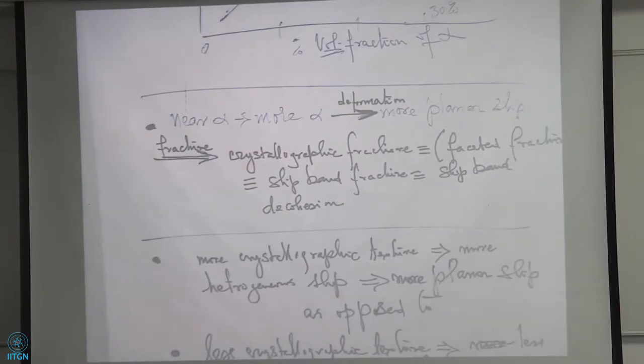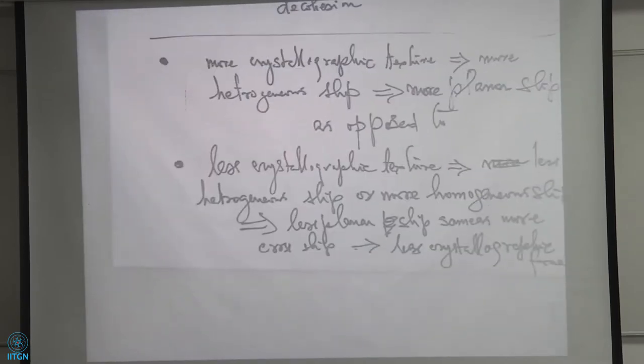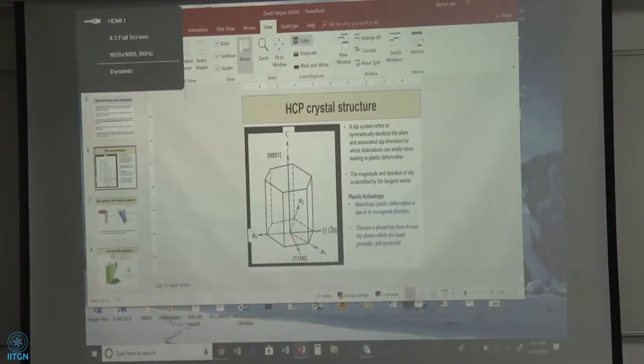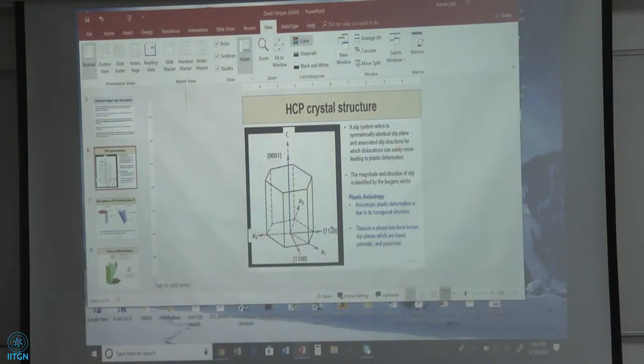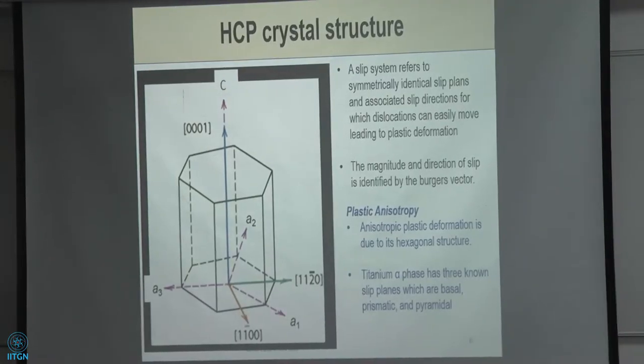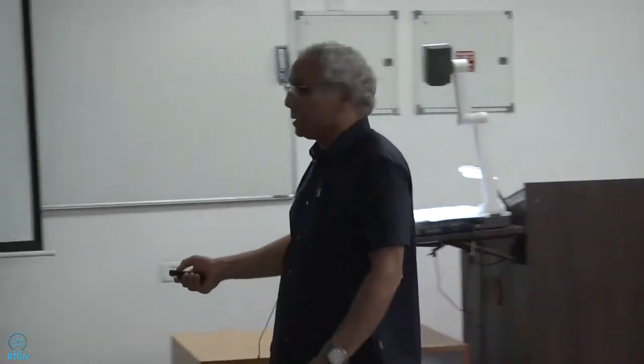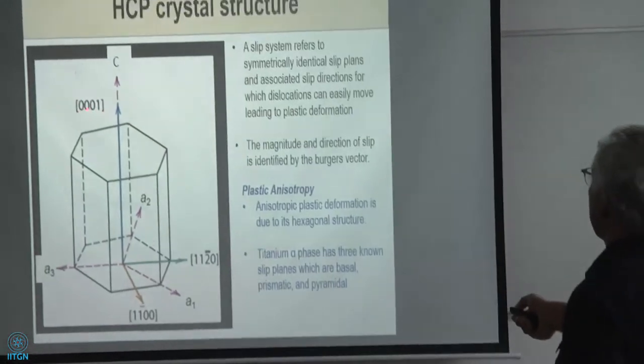So here are some observations. And we said, before you just came, that near alpha alloys like 6242, with silicon or without silicon, if you put silicon there, 0.2% silicon, it's more a weldable alloy. We add silicon sometimes to this 6 aluminum, 2 tin, 4 zirconium, 2 molybdenum or something. Right? And then the titanium 811, alpha beta, near alpha alloy with beta phase also there. And these are very crystallographically textured, meaning they show a lot of planar slip. The dislocations move in a planar slip. They're very textured. And also texture comes from a different place, which we will see. You already know that, but I'm going to point it out.